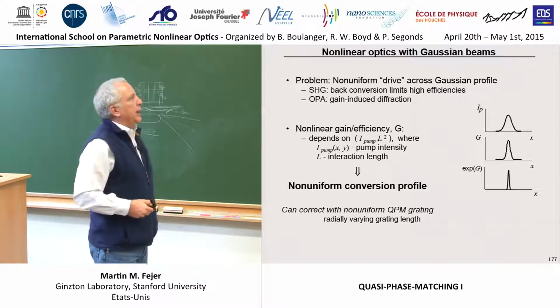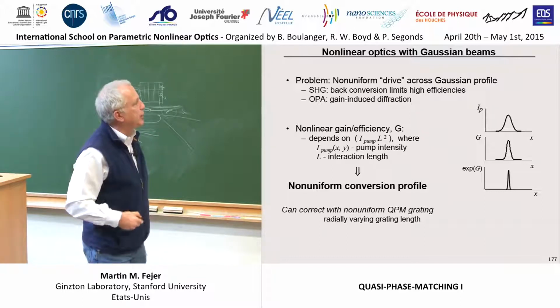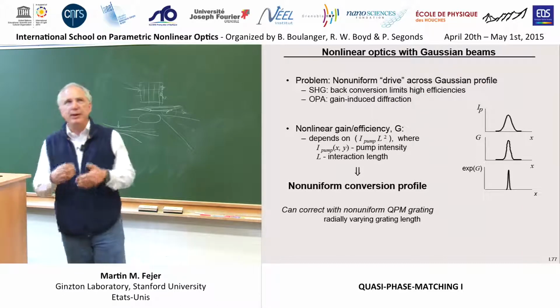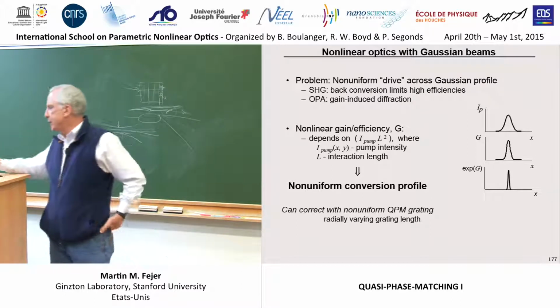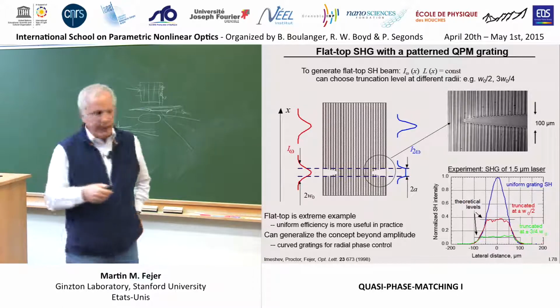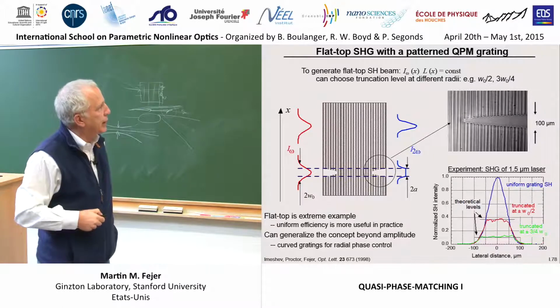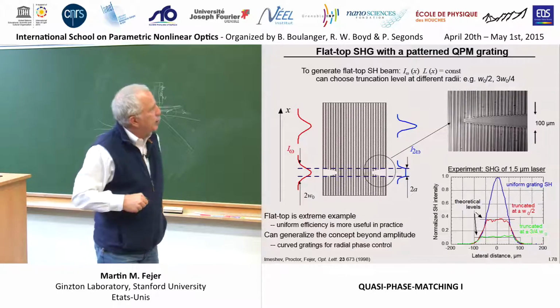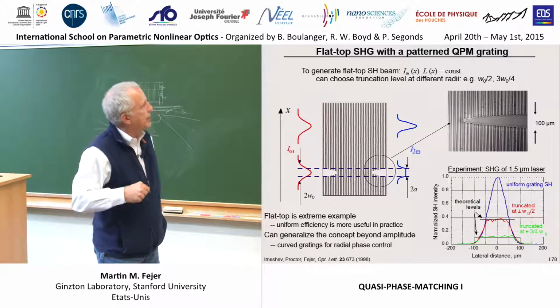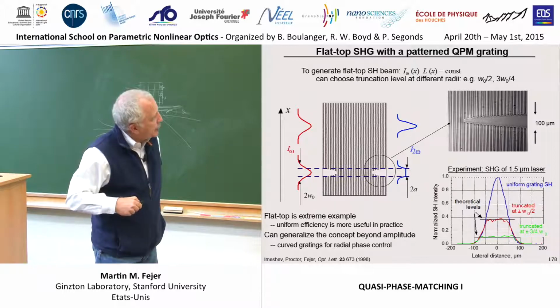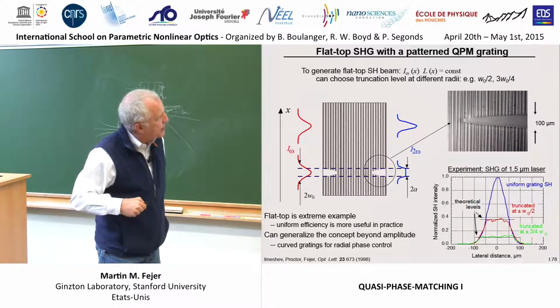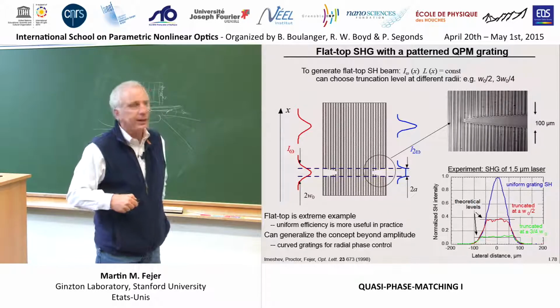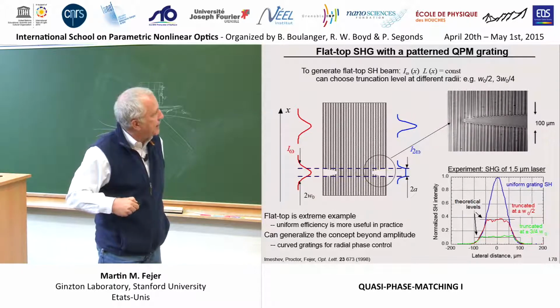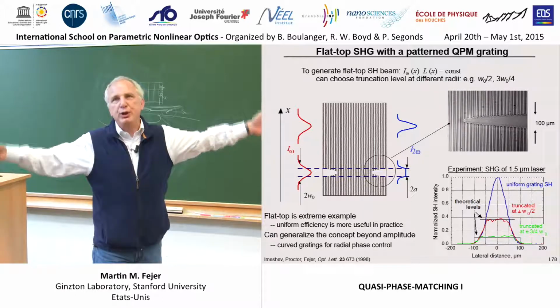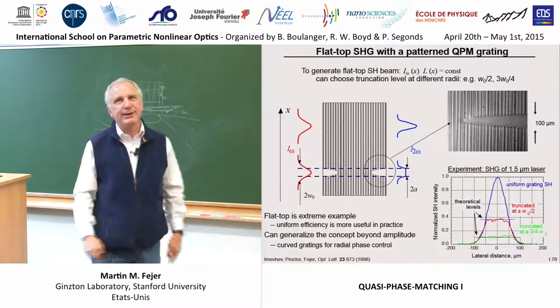So one tool you can use to try to fix that is to manipulate what the radial variation of the gain is in your structure. And since the gain is proportional to the length, if you were to make a QPM grating that was not uniform across the aperture of your beam, but was shorter at the center and longer at the edges, just by not poling these regions, then you could make the product of the intensity and this length, and the lower intensity and that length, over some portion of the Gaussian beam. You can flatten this thing out.